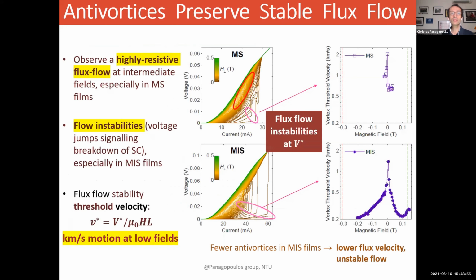Notably, the anti-vortices also preserve stable flux flow. What we see here is in the IV characteristics that I have plotted in the middle, in the MS and MIS samples. When you look into the details in the circled areas, there is a high resistive flux flow at intermediate fields, especially in the MS films. And the flow instabilities show clearly in the MIS films. You can see these very beautiful jumps, voltage jumps, signaling the breakdown of superconductivity.